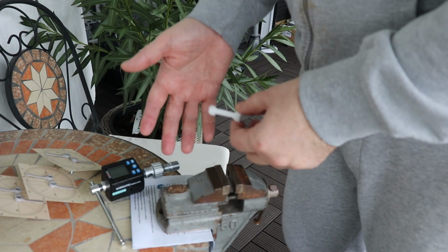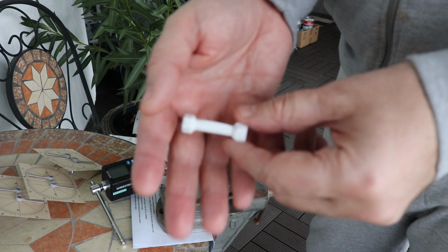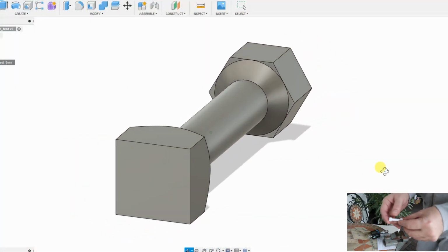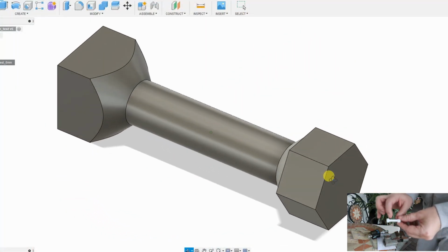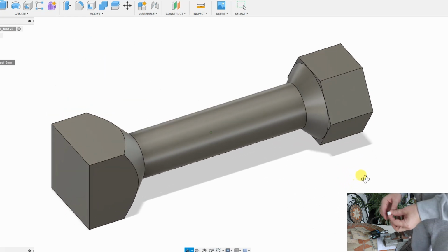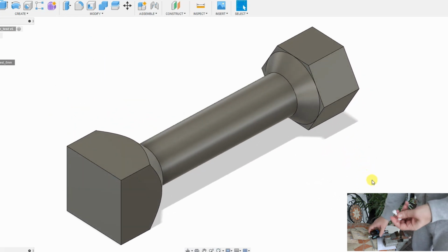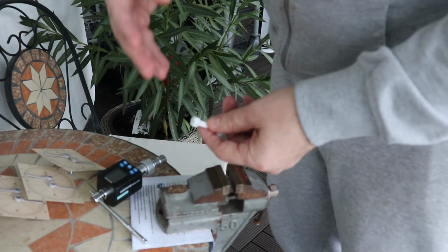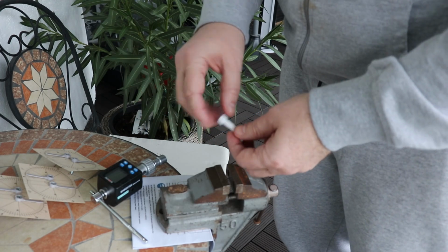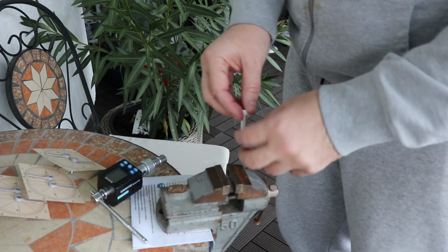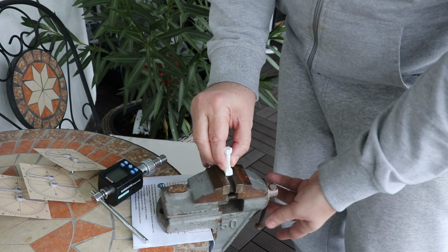In this torque or twist test, I have this 6 mm diameter cylindrical part. The length is 22 mm, and this side goes into the vise and the other side goes into this torque meter. And I want to record the load at 90-degree angle, the maximal load, and maybe the maximal deformation. I'm starting with ABS.